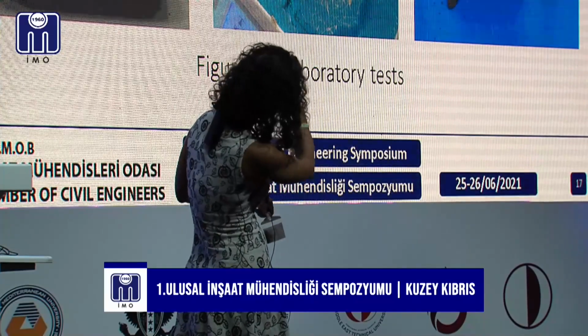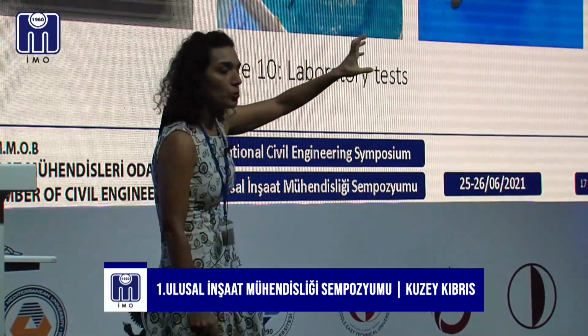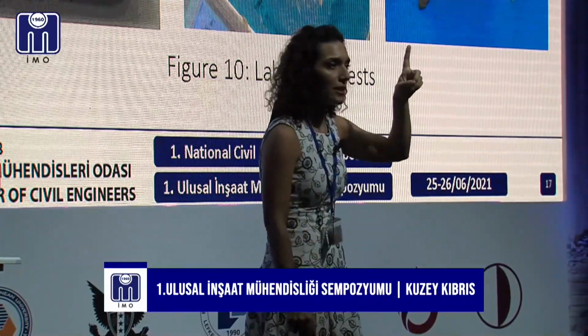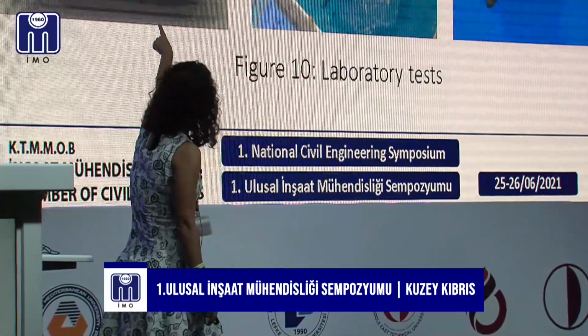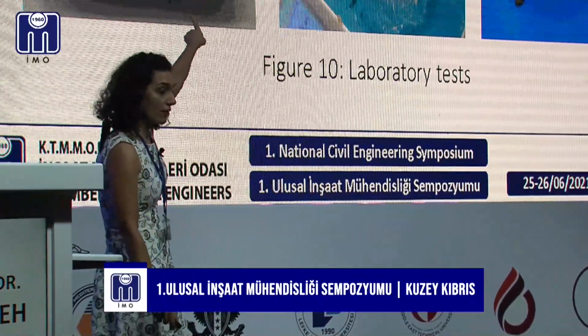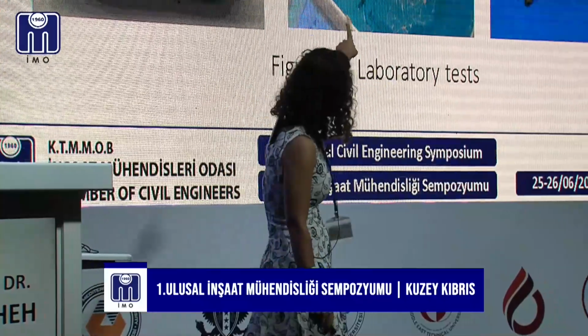So here I want to show you the kind of fiber that I'm talking about. It's like trash. So the thing is that we use 0.2%, 0.3%, and 0.4%. So when you say 0.2%, they will think that that's such a small amount. But because the plastic is very light, you can see that 6 grams of it will make such a big volume. So that's the look of it after being compacted and the look of it after being crushed.